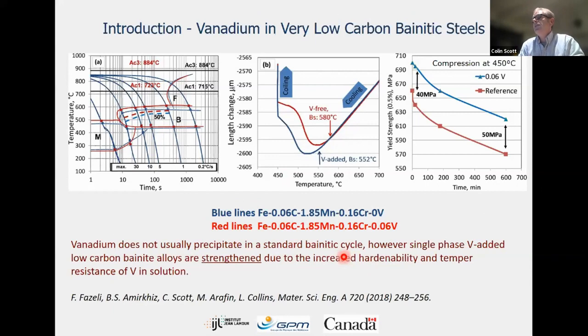One of the first things to think about, if we're looking at vanadium in bainitic steels, is what we already know. And there's a lot of work being done on very low carbon bainite steels. So these would be things like line pipe steels like X80. And what we know is that adding vanadium to those steels does improve the mechanical properties. They get stronger. And the reason for that is nothing to do with precipitation. It's simply because we have increased hardenability due to solid solution vanadium. And we also have this temper resistance effect of vanadium that's well known in martensite, but it also applies in bainite.